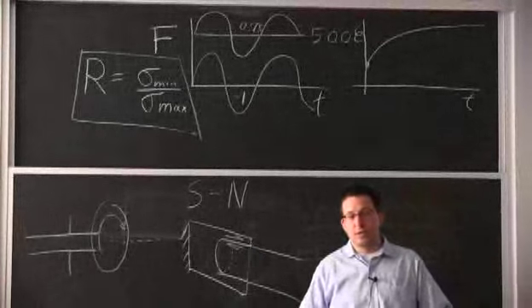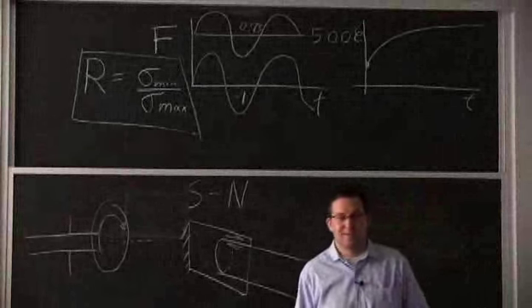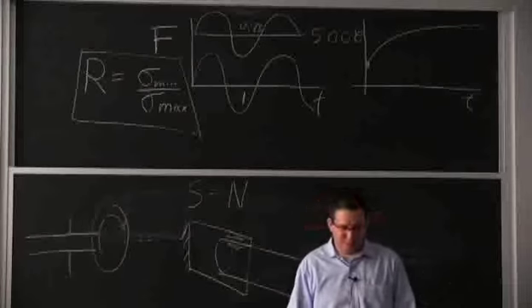And that was the case for those titanium ribs for the front fuselage, because they can't be inspected easily. The way we designed them is we allowed for a crack to exist from the beginning, and through the 30,000 up and down cycles that were anticipated, that crack would not grow to a size that would create an overload fracture. So it was a conservative approach because we really could not inspect that specific structure once it's all built together with the skin on top and all the rivets in different directions. That's what you've got. You can't do anything about it.